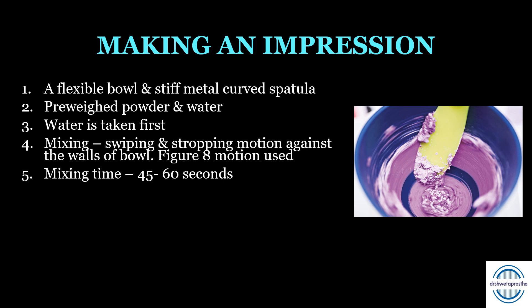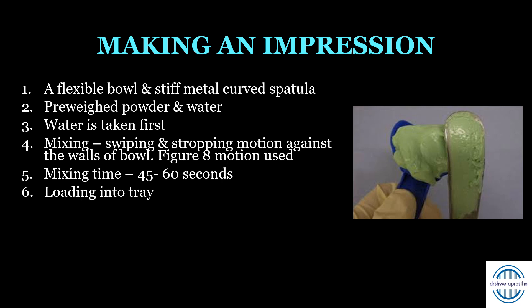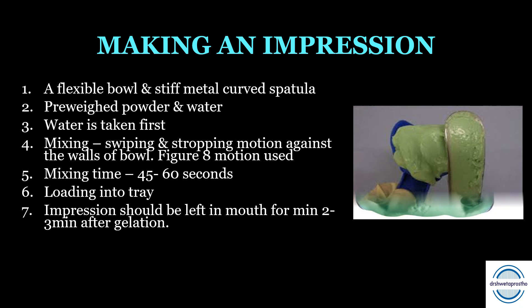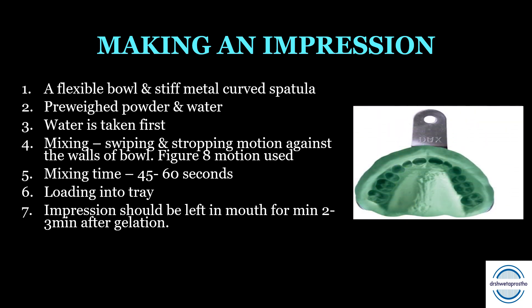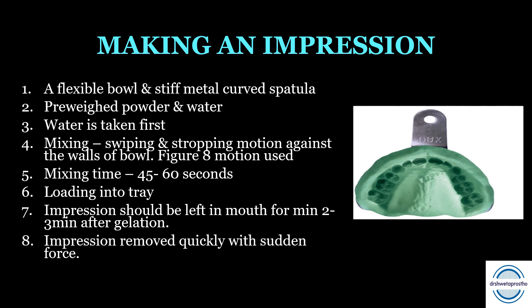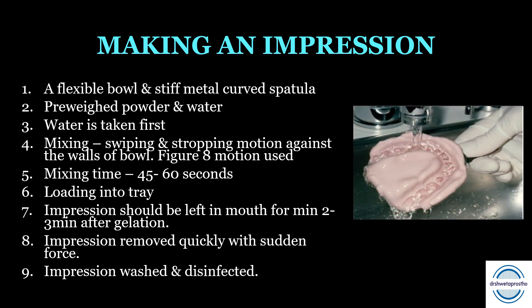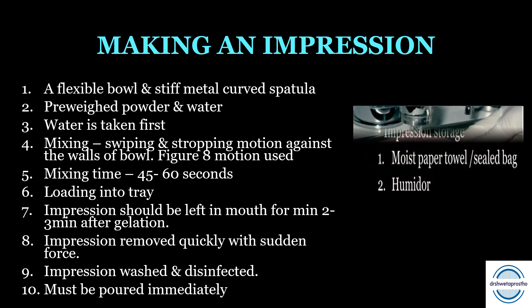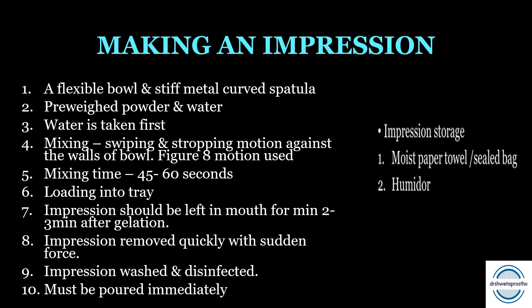The impression material is loaded into the tray and left in the mouth for at least 2 to 3 minutes after initial gelation to increase strength and elasticity. The impression should be removed quickly with a sudden force — a long gentle pull can cause the alginate to tear or separate from the tray. The impression is then washed with cold water to remove saliva or blood and disinfected by spraying or immersion with glutaraldehyde or iodophor. The alginate impression should be poured within 15 minutes. If storage is necessary, wrap in a moist paper towel or sealed bag to maintain 100% humidity, or store in a humidor.